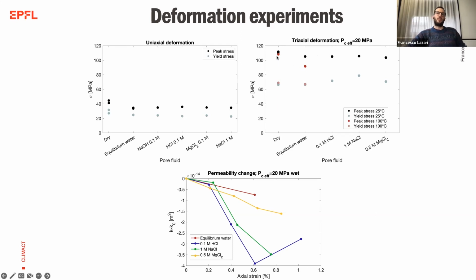While if we look at the experiment at 100 degrees, we have basically the same strength in the dry sample, but the wet sample with water is quite considerably weaker than the dry one, which means that when we increase the temperature, the presence of water becomes much more important than at room temperature.